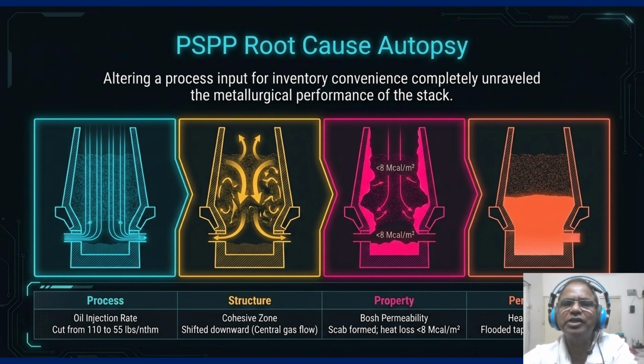So this led to a failure in the property, that is, Bosh permeability vanished as a scab formed, dropping heat loss below 8 megacalories. So finally we hit performance. Hearth drainage failed, the tap hole flooded, and we ended up with a chilled or frozen hearth. The so what factor is that a simple inventory decision unraveled the stack. If you change a process input without modeling the shift in the cohesive zone, you are gambling with the furnace life. Everything is connected in this metallurgical chain.